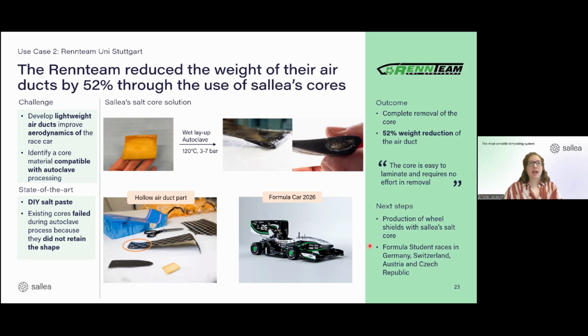And the way they are doing these parts at the moment is they tried to do it with a do-it-yourself salt paste, as it is suggested here. And as you can imagine, it actually failed because it basically couldn't retain its shape, but also even because it couldn't retain its shape, I think there was even some corrosion in the autoclave, which was really not great. And this is why they were really excited about our salt core technology.